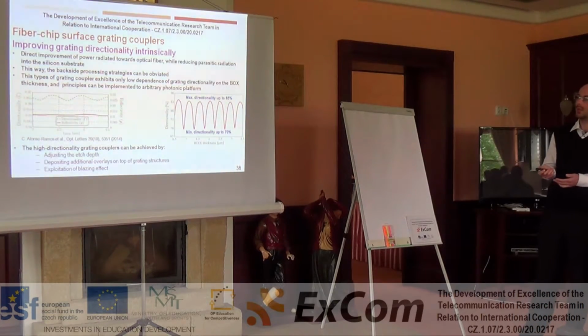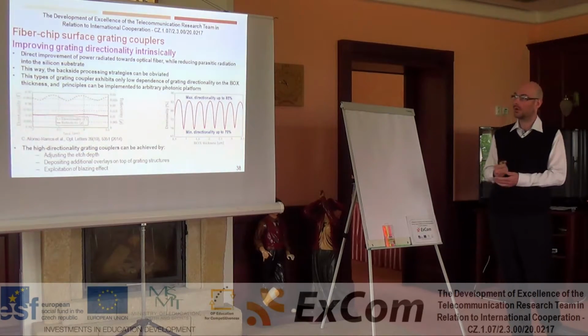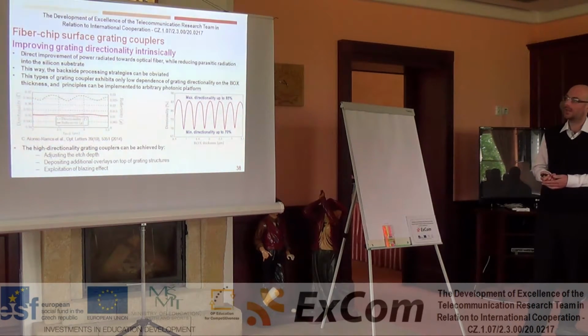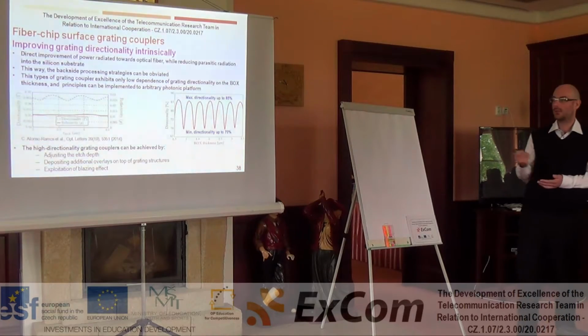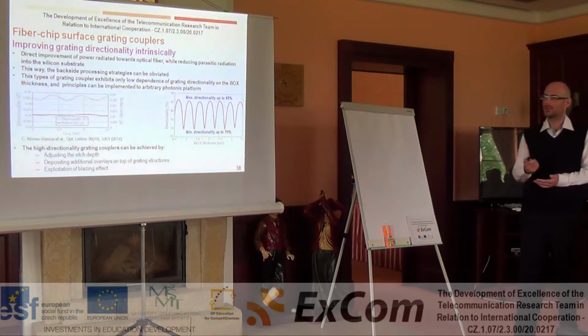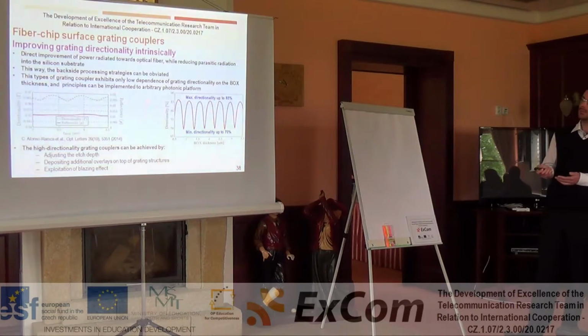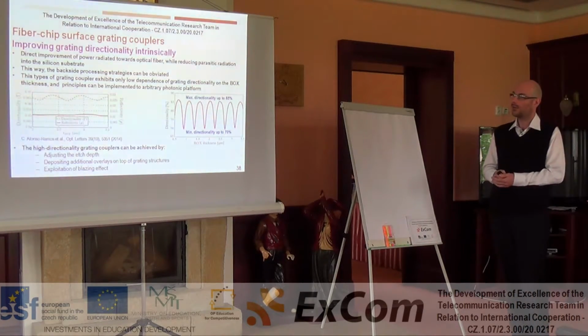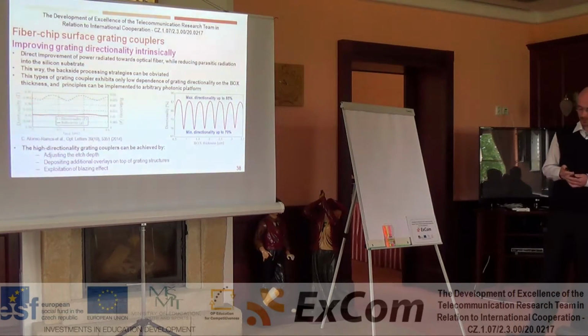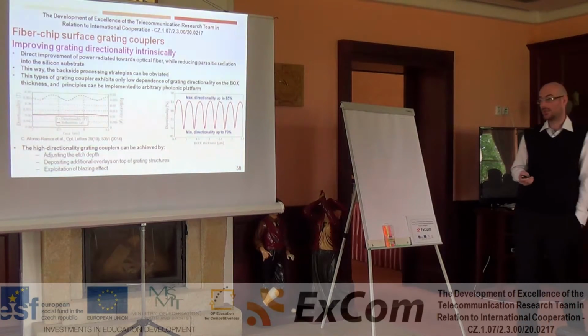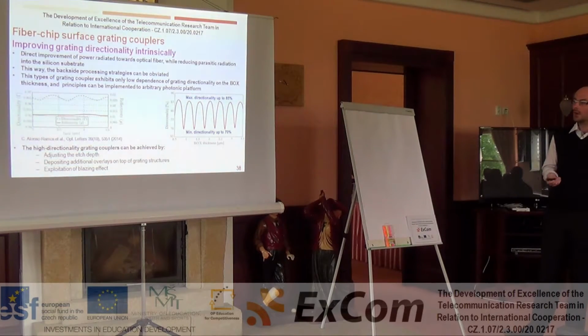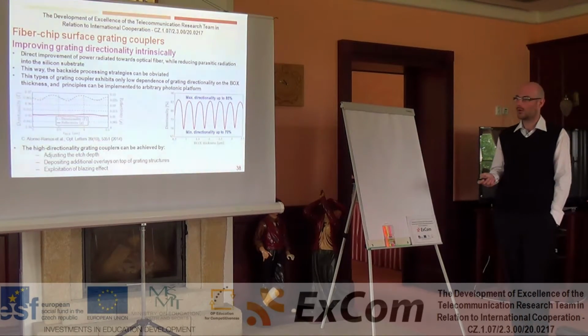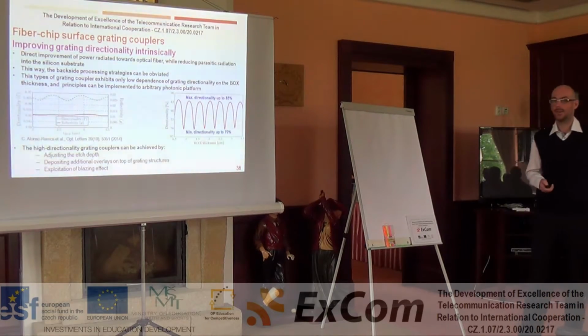This type of grating coupler exhibits only very low dependence of grating directionality on the BOX, as I mentioned before, which is very critical, and in principle this can be implemented for an arbitrary photonic platform. High directionality grating couplers can be achieved by adjusting the etch depth in the grating region, by depositing additional overlayers on top of the grating structure, or by exploiting the blazing effect in the grating.